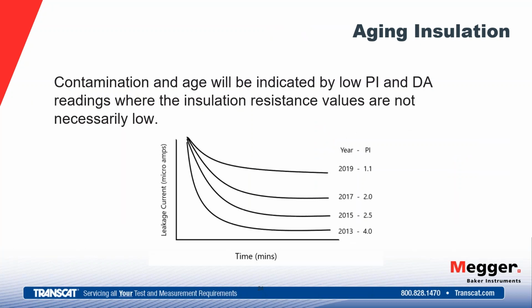In the PI, we also see the effects of aging. Contamination and age will be indicated by low PI or DA readings, where the insulation resistance values are not necessarily low. So here we see, over time, the progression of contamination and/or age. If it's clean and dry through this period, then this is an indication of age. As we take data points, here every 2 years, our PI values are steadily getting less due to contamination or age of that insulation. Contamination is what we first suspect. If that motor is clean and dry, then we suspect age of the insulation.